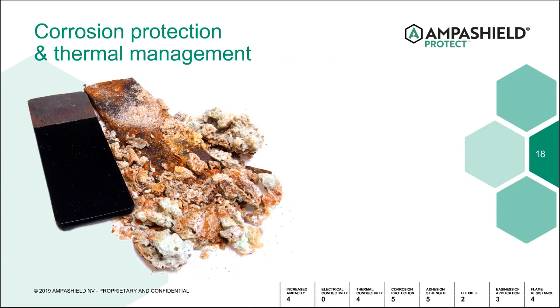Now you see on the screen there two pieces of basic carbon steel. One is bare carbon steel, one is carbon steel coated with Ampashield Protect. They're both immersed in sulfuric acid, a 10% concentration at 65 degrees centigrade for 48 hours, which is basically the immersion time. You can see on the right-hand side, complete disintegration. On the left-hand side, no effect.